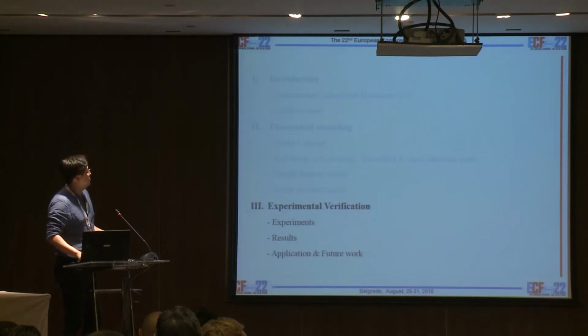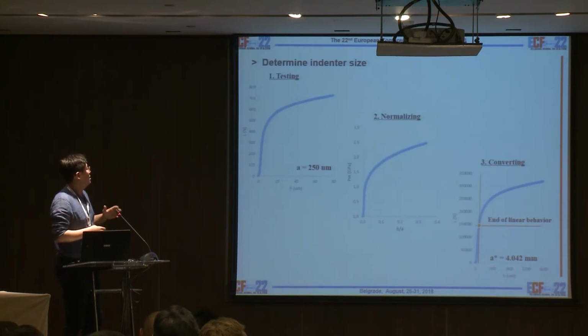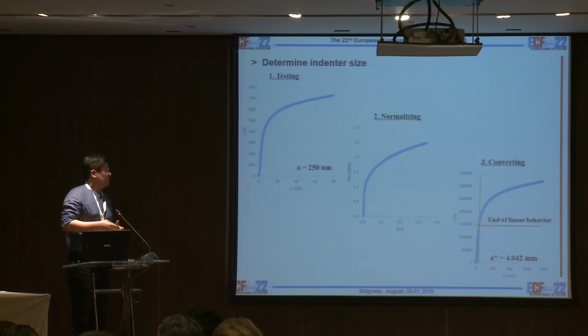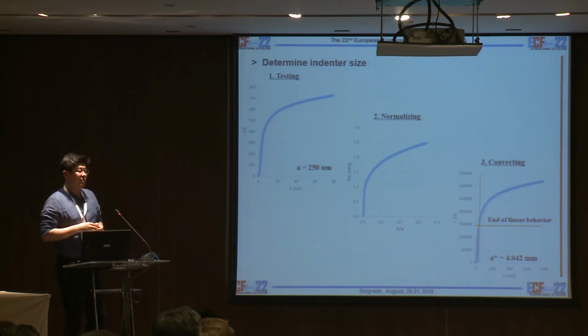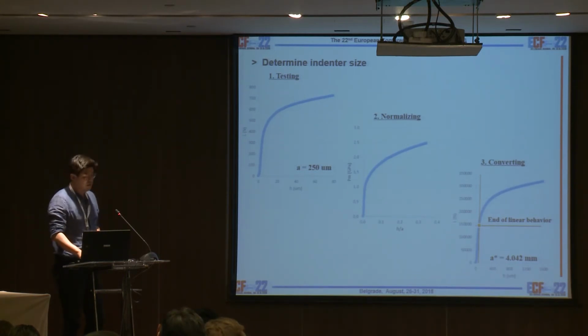Same as the procedure in the ductile model. So we tested with the 250 micrometer indenters and normalized it, found the intersection with the 0.2% offset line, and that is the correct initiation point. And we got an A-star 4 millimeter size virtual indentation size curve, and then calculate the fracture toughness.